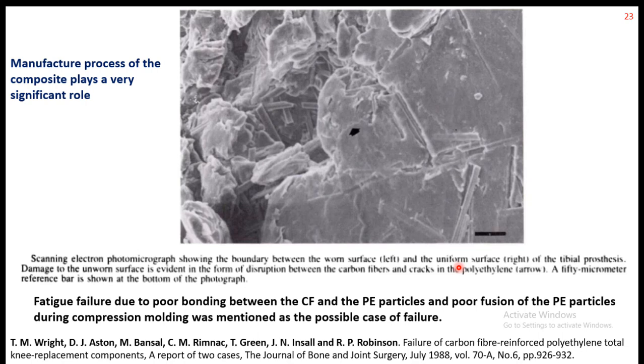The authors of this paper found that the failure was related to poor bonding between the fiber and the matrix - matrix being UHMWPE and fiber being carbon fiber. So it was more of a manufacturing issue rather than a material issue. Perhaps this type of system can be tried again, and the manufacturing part has to be resolved - the bonding between fiber and matrix has to be good. Fatigue failure due to poor bonding between carbon fiber and polyethylene particles, and poor fusion of polyethylene particles during compression molding, was mentioned as the possible cause of failure. However, these composites have not been tried since then, basically out of fear about the issues that happened for these patients.